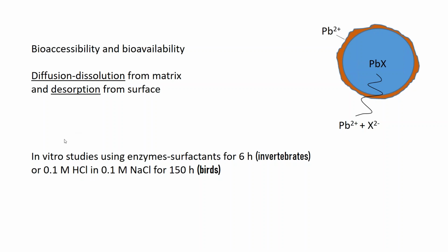And we can assess this in two ways. We can simulate the digestive conditions in two representative types of organism. We can mimic, if you like, an invertebrate by exposing this sample to enzymes and surfactants for about 6 hours. So 6 hours is the passage time in the guts of a typical sediment-feeding invertebrate, and its gut is made up of enzymes and surfactants. Or we could expose this to a weak acid in a sort of saline solution for 150 hours, or possibly more. Some birds take in plastic and it stays in their digestive system for days, possibly even months, some studies suggest. So it's a much longer term experiment here.